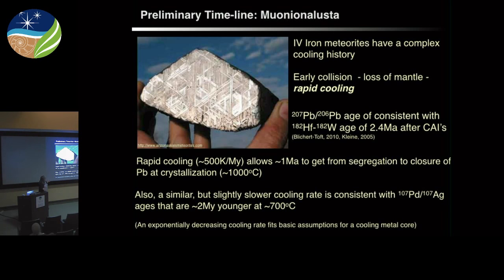Right, but right now we have some lead ages that are very old and potentially consistent with something close to, or not that long after, the segregation that we know from hafnium-tungsten isotopes. They're also less far away in temperature than we thought they were before. They're maybe only a few hundred degrees cooler. And even with rapid cooling, we can get down to the closure temperature of lead within a very short time span of 1 million years or so. A slower cooling rate can get us from there to the palladium-silver closure at around 700 degrees Celsius.